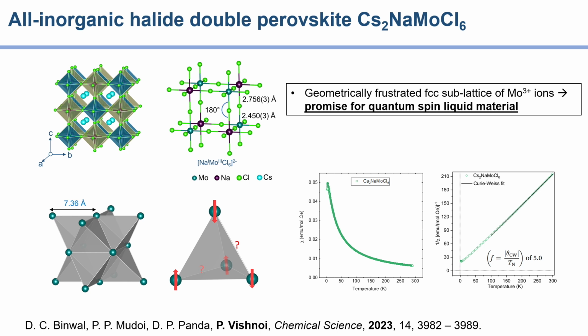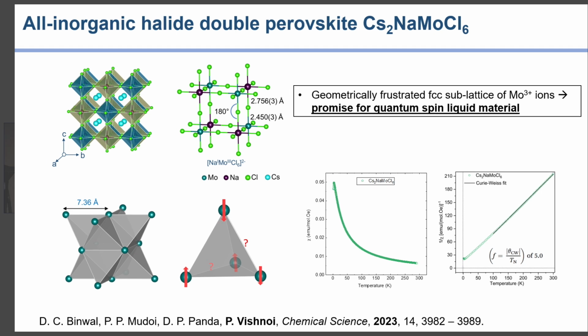When we had methylammonium in the system, the old compound, I showed a series of compounds which are one-dimensional, not only in molybdenum, but also in ruthenium. But the moment you change to cesium, it becomes a 3D lattice. So it's cesium-2 sodium molybdenum chloride 6, a double perovskite with a perfect cubic lattice. And we also checked the possibility of phase transition.